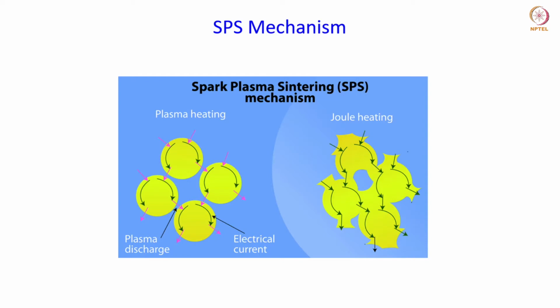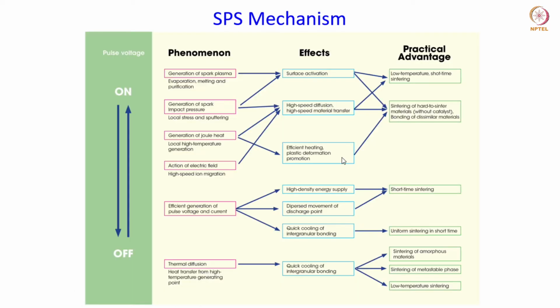So when you talk about the SPS mechanism, it is basically the plasma heating and the plasma discharge which is set up in the gap between the particles, and that ultimately leads to this Joule heating, which results in heating of the compact and densification. Okay, so here the electric field is applied through a DC pulse which is on-off type. So during this pulsing of the current, there are different phenomena which take place, and each of these phenomena has its own effect on the densification process and the densification mechanisms which occur during SPS.